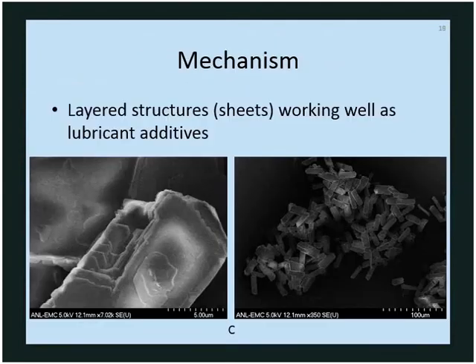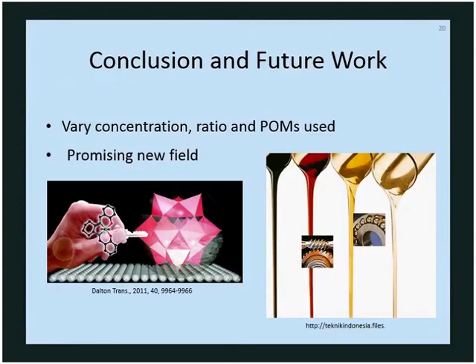So this is just higher resolution scanning electron microscopy images of the ratio synthesized. And it's found that a layered structure of sheets works well as lubricant additives, so that it provides better protection and possible tribochemical film formation. And then varying the percent weight concentration, varying the ratios, and the type of polyoxometalate used provides for future work for this project. And it's a promising field combining the fields of chemistry and tribology.